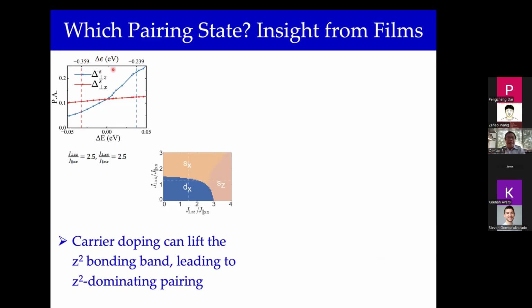And in fact, there are seemingly conflicting conclusions even in the ARPES spectrum for these films. And we claim that it's in fact natural because of this variation of the level spacing in the different films, and also the possibility of a different amount of carriers when you anneal or otherwise do something structurally or procedurally to these films.